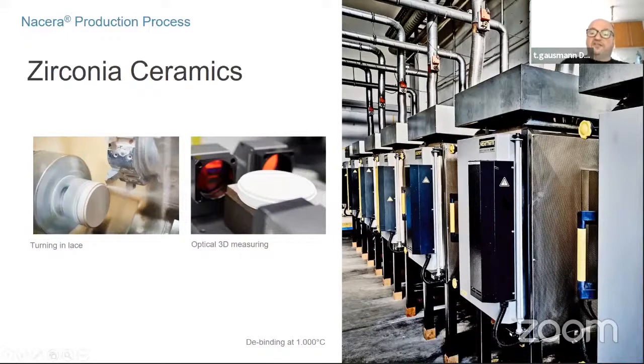What we do differently is we unpack them from the furnace after 2 days, when they cool down from 1000 degrees. And each of our discs is measured individually on this optical 3D measurement. So you don't get an average shrinking factor for everything in the furnace, because with the temperature in the furnace,